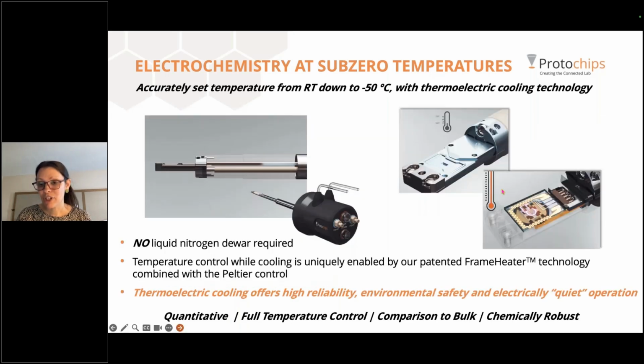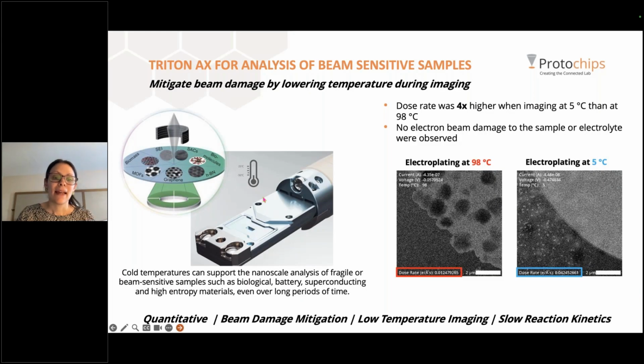So to modulate the temperature, you'll run the Peltier device, so the cooling will take place, and then simultaneous to that, the heating coil, the frame heater technology I was talking about earlier, will compensate and help modulate the temperature if you're trying to go to minus 25 or minus 30 or 0 degrees, somewhere in between that range. And so the two will work together to heat from the cooled temperature and help you modulate in the middle of your experiment to whichever temperature you would like to call for. And so that's the operation of the Triton system itself.